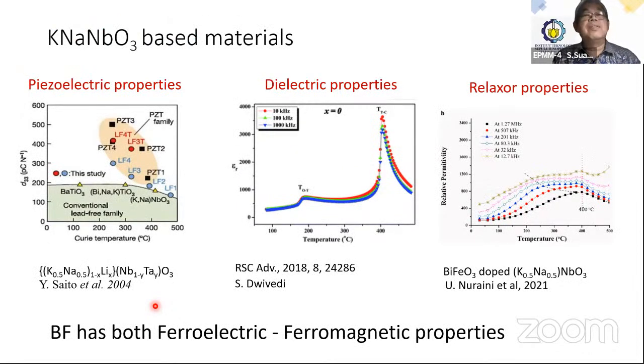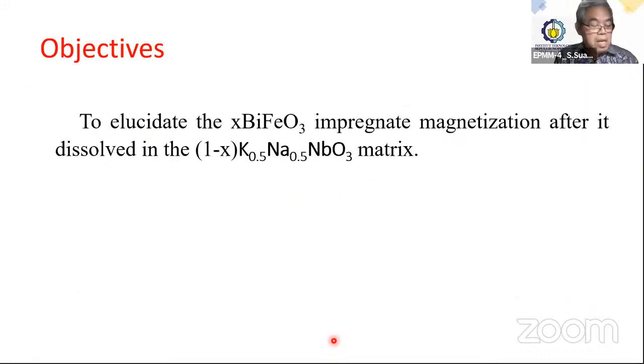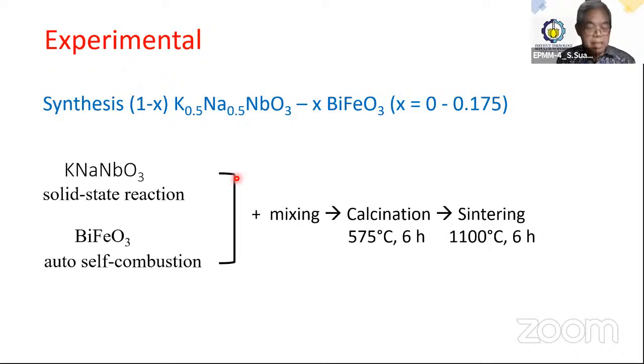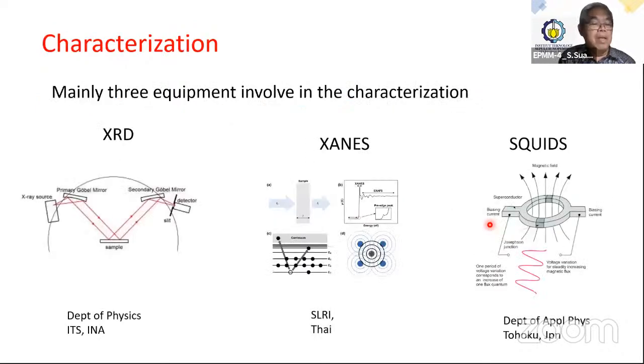Our concern now is the KNN-based materials. The KNN materials are of great interest because they have multiple properties such as piezoelectric, dielectric, and relaxor. On the other hand, bismuth iron oxide has both ferroelectric and ferromagnetic properties. Now, our objective in this work is to elucidate the bismuth iron oxide's impregnated magnetization after it dissolves in the KNN matrix. To fulfill this objective, samples were prepared from powder synthesis up to sintering. After that, the samples were characterized through XRD for phase identification and structure determination, XANES for oxidation state determination of iron, and SQUID for magnetization.